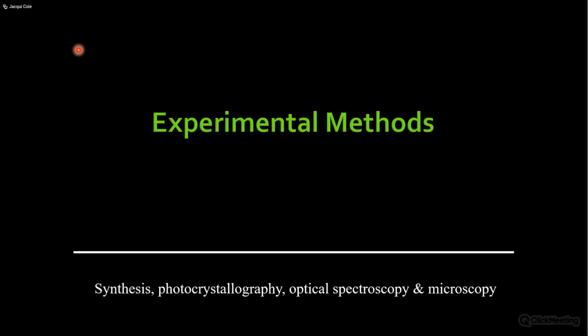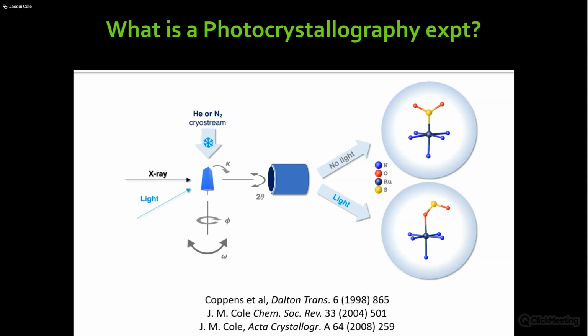So how do we even do these types of experiments? So in terms of the diffraction, we essentially use a technique that's become known as photocrystallography. In essence, it is an in situ X-ray diffraction experiment where you shine light at the single crystal. This is a crystallography apparatus, and first of all, before you shine light, you will do a standard crystallography experiment. So you obtain the crystal structure of the material in its dark state.